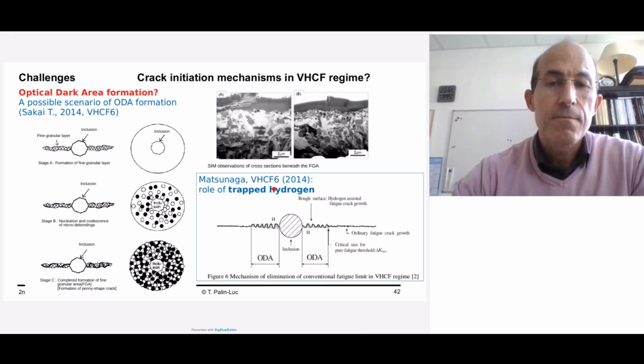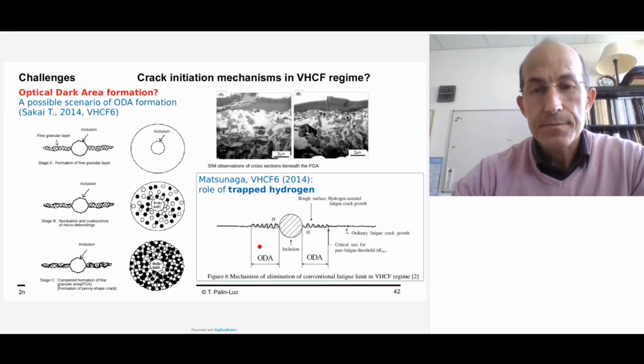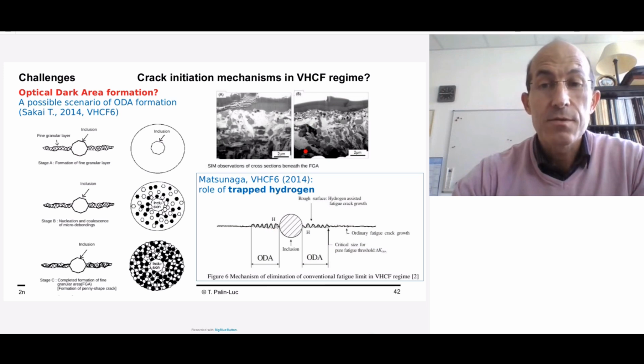Another important thing which is proposed by Matsunaga in the same conference is the role of trapped hydrogen. Hydrogen is trapped around the inclusion. This is known in metallurgy. And he said that the effect of hydrogen is to embrittle the material. So around the inclusions, the lower ductility of the material is favorable to the creation of micro cracks. Then the micro propagations plus the nanograin appearance due to the recrystallization create an optical dark area on the microscope. But these two explanations have to be confirmed, because there are no other authors able to observe such mechanical effect and such chemical effect. It is very difficult to measure the quantity of hydrogen around one inclusion.